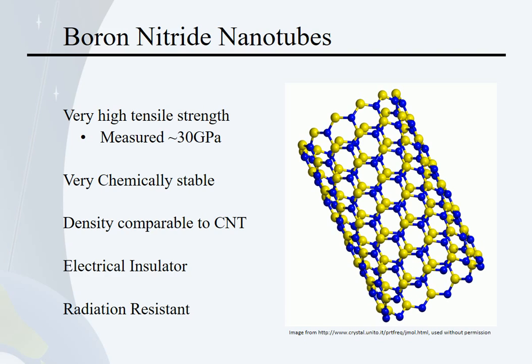While boron nitride is very, very stable chemically, it's much more stable than nanotubes, its stability goes above and beyond. It doesn't really have any oxidation behavior, let alone any oxide issues or oxide losses. And you see the same thing with reactions with strong acids, strong bases. Boron nitride is not inert by any stretch of the imagination, but the things you have to do to get it to react are incredibly aggressive, chemically speaking. So it's incredibly stable. It's also an insulator.